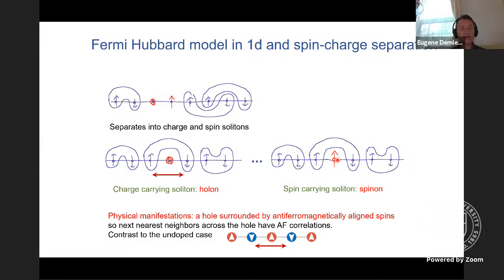And what people realized early on is that if you look across the holon, for example, then spin correlations look as if this holon was not there. We just have to remove the site with the holon. So in particular, if we compare the spin correlation of two sites, where one site is on the left of the holon and the other is on the right, they're most likely to be antiferromagnetically correlated. They make a singlet with each other. And this is very different from, let's say, the system where there are no holes, right? Because now we're looking at sites which are two lattice sites away from each other. So in a perfect antiferromagnetic state, they would be ferromagnetically correlated, but now they become antiferromagnetically correlated. So technically we often call it a domain wall across the soliton.